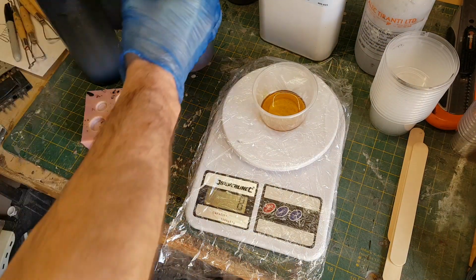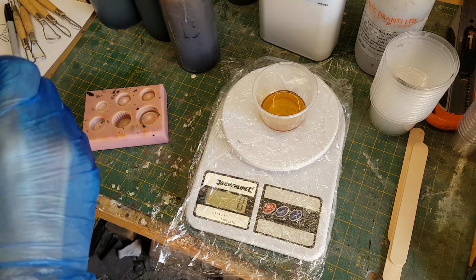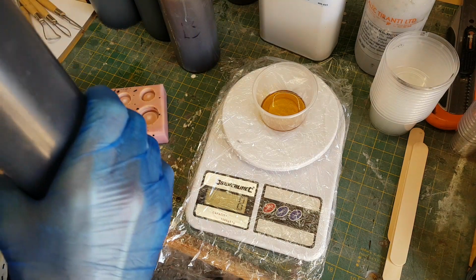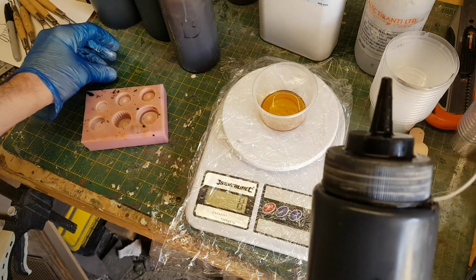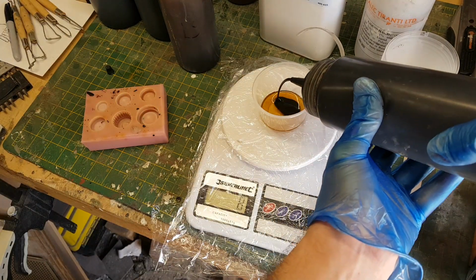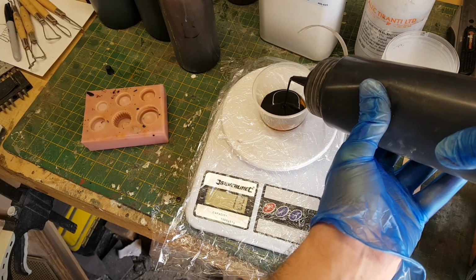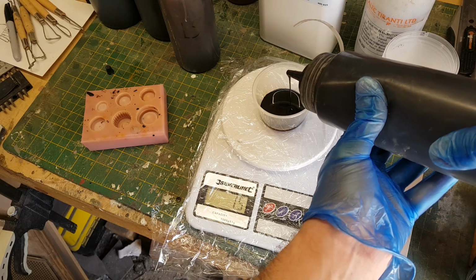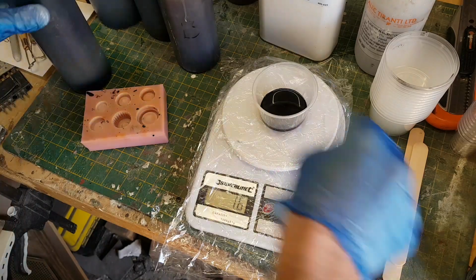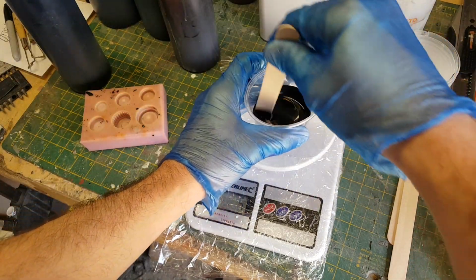So I put 8 grams of the first part of the resin on there. One way of doing this could be to have two separate cups and get accurate amounts of resin in both. The problem with that though is that the resin in one of the cups, once you pour them together, won't cure. So you end up wasting one of your cups. So what I've learned to do is just be quite careful and add exactly the same amount of both parts of the resin to the same mixing cup.